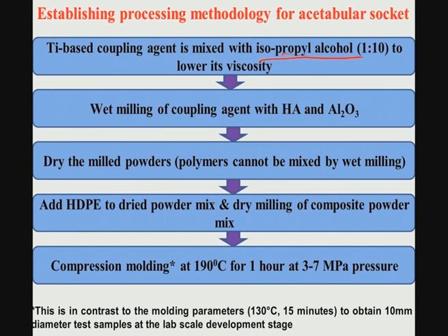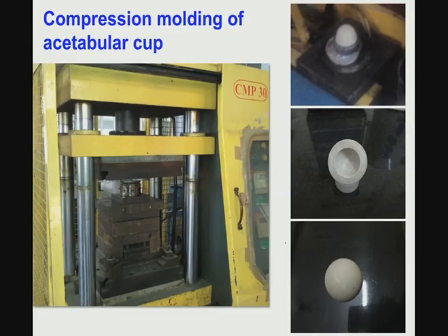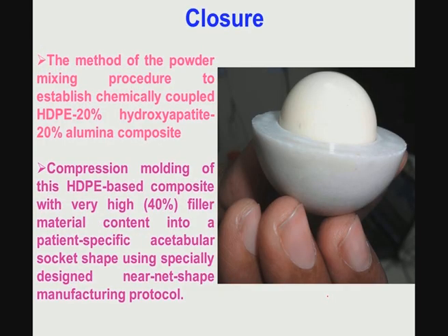and isopropyl alcohol is the medium used to mix the coupling agent with the powder mix. After that you can do compression molding of this large acetabular socket type of device at 190 degrees Celsius for 1 hour at a fairly moderate pressure of 3 to 7 megapascal. This is how the compression molded socket looks, and this is your as-fabricated near net shape. So, you do not need to do any machining to get the final shape, and this is an illustration of near net shape fabrication of the acetabular socket.